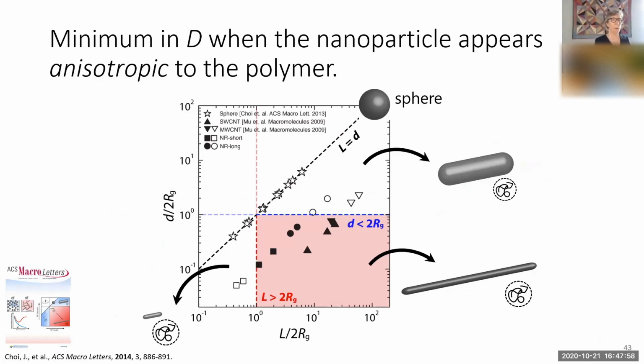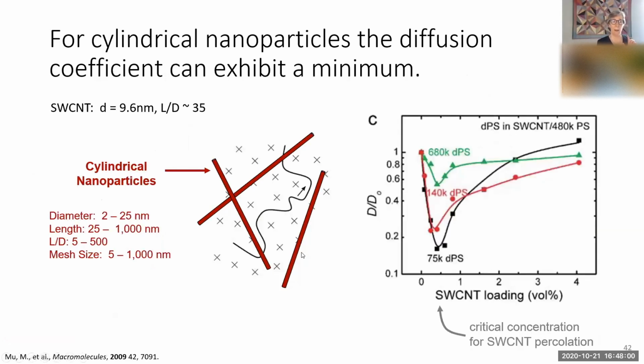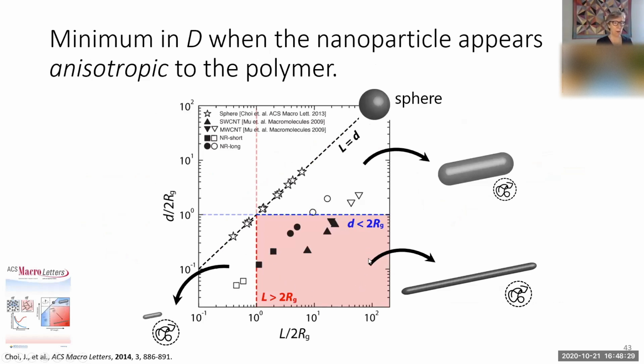Sure. So what we were tracking was whether or not there's a minimum in the diffusion coefficient as you put more nanoparticles in, right? So when do you see this minimum? Because we were able to make it go away even in nanotubes if we had certain sizes. Anyway, so when do you have this minimum and when does it just monotonically decrease with the addition of particles? And so this red zone is where you see this minimum. And you see that minimum in the diffusion coefficient because the polymer detects an anisotropic particle.